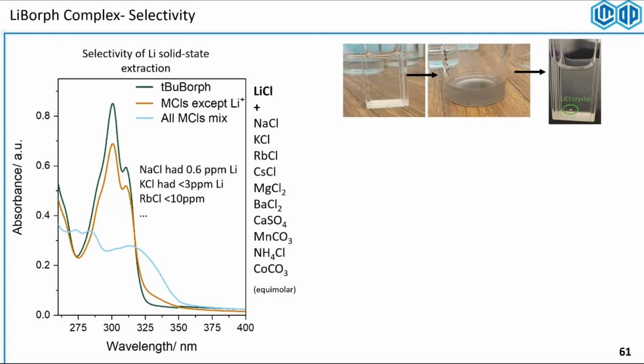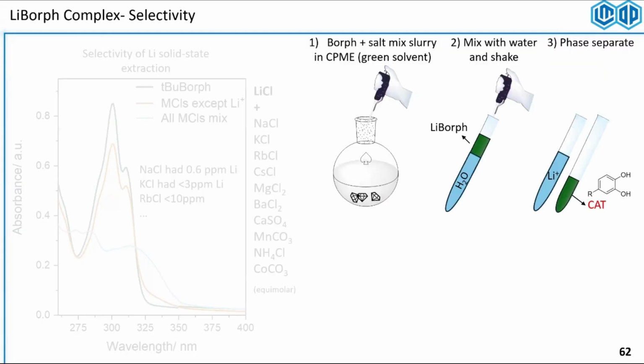And later, the PhD student that was working with me found that this small shift here is not because of binding to the other metal ions that we have. It's perhaps because of the tiny amount of impurities that we had already in the other salts of sodium and potassium and rubidium that we were working with. So we took this one step further. We thought of now a way to extract lithium from mixture of different salts.